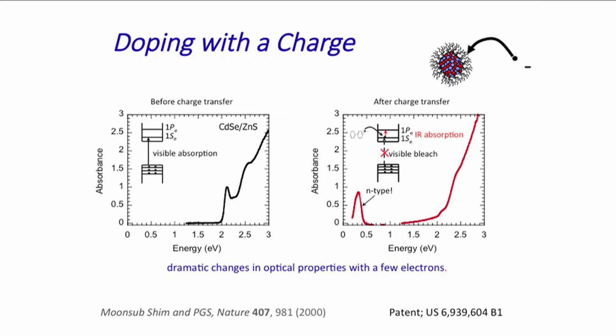And you can dope by charge transfer. This was done in 2000. You take a quantum dot, you find something that is sufficiently reducing so that the electron can go into the dot. And for the first time, we were able to see the effect of this occupation of electronic states by the electron in the optical spectrum, with what we call the intraband transition, which is a transition between the states of the quantum dot at this level. So here I'm getting quite technical. That transition is direct evidence that there is an electron here. So we knew how to dope, but it was not very convenient because that was done in solution.